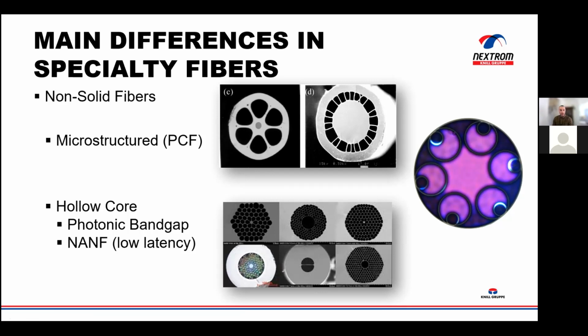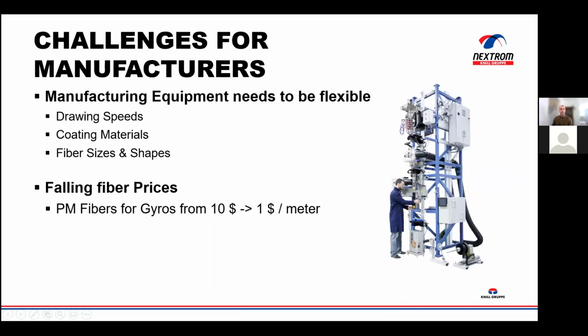Up until very recently, there's been significantly higher attenuation in these hollow core fibers, but just, was it 2 weeks ago at OFC conference, Lumenisity announced quite stunning results on their anti-resonant nested fiber, which is this one here, where they were getting better attenuation and across a wider band than a standard single mode fiber. So that was a quite promising development from them. So those are the varieties of different fibers. And you can see from that there is a huge difference of equipment that would be needed in order to make all of those.